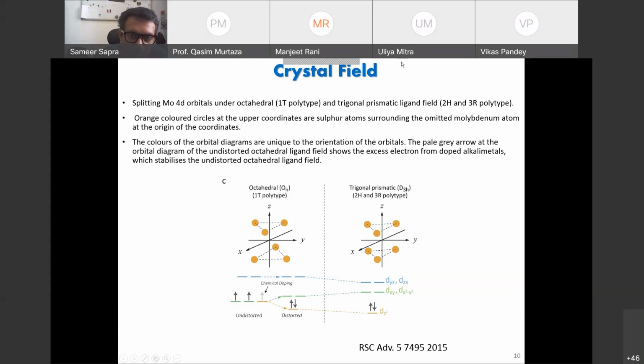But then how does the 1T polytype come? The 1T polytype comes in the presence of some of these metals. For example, when you want to make 2D materials, you take the bulk material and you have to exfoliate it somehow. And people do it in the presence of lithium. Now, what lithium does, the lithium metal gives off an electron to molybdenum sulfide. Okay. And it comes and sits between the layers. Okay. So it exfoliates the layers, it expands these layers and throws them apart. But it sits over there with the electron coming in over here. Okay. Now this scenario becomes more stable and the 1T polytype is then stabilized. In fact, the 1T polytype is known to be metallic. And it was discovered it's because of the electron of the lithium that comes in that the metallicity comes about.